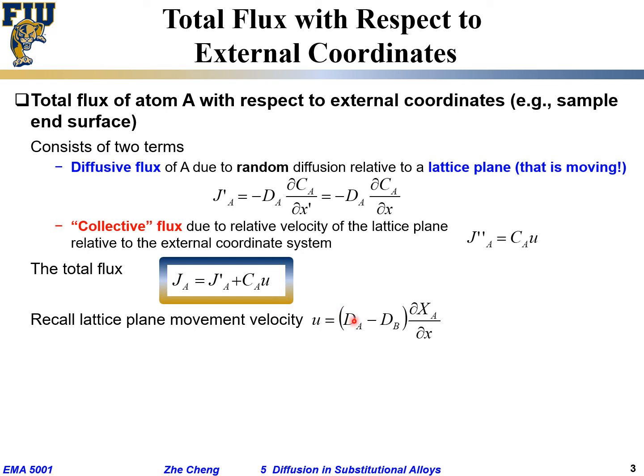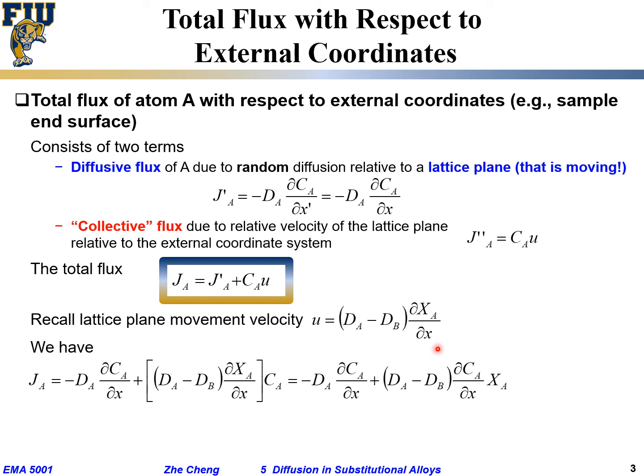We said the velocity from Darken's first equation is just the difference between the diffusion coefficients times the mole fraction gradient. Okay? And then, that's just pure mathematics. What is our JA prime? JA prime is just this term, right? It's minus dA times the partial differential of Ca with respect to x, plus Ca times U. Within the square bracket, U is the velocity of that moving interface.